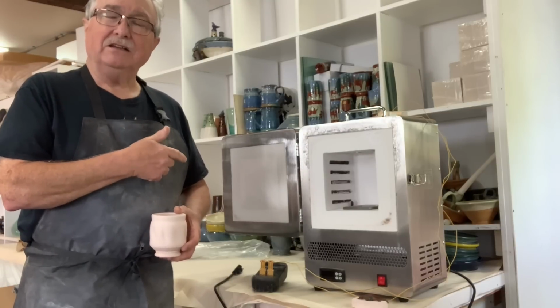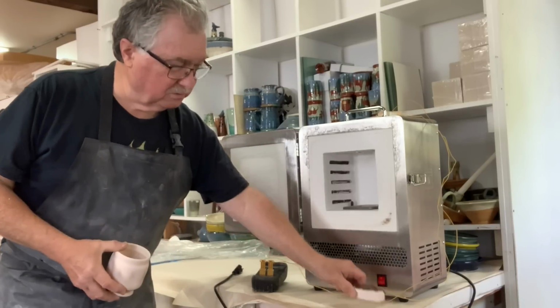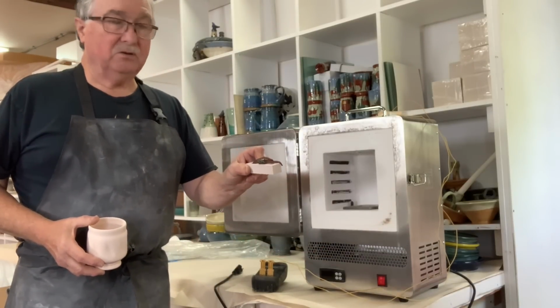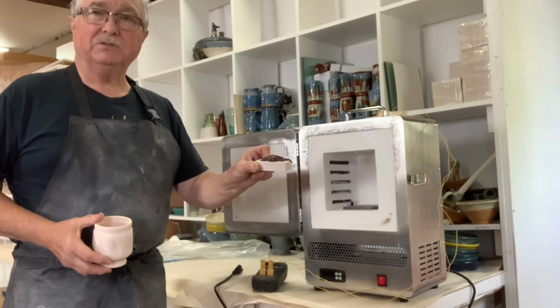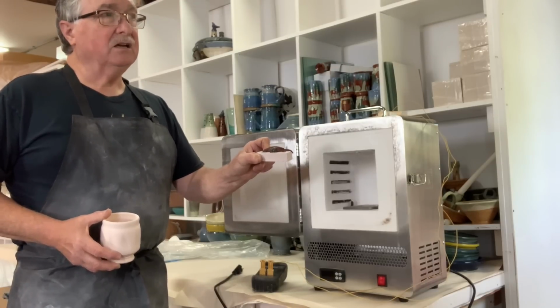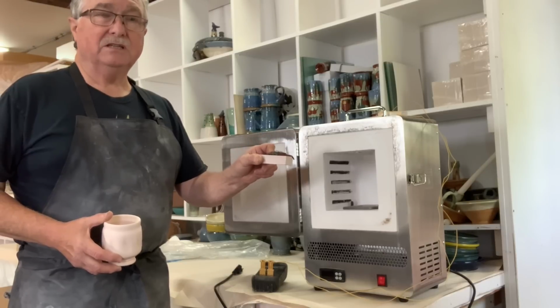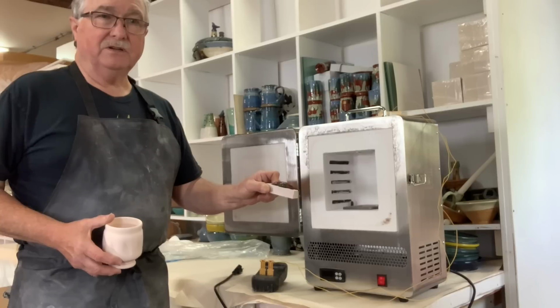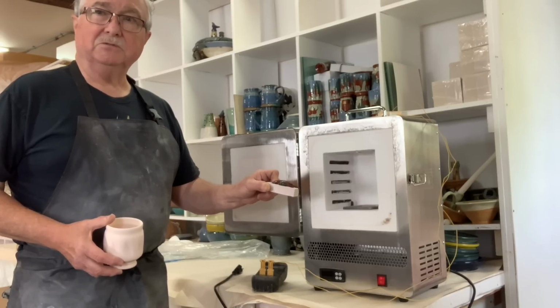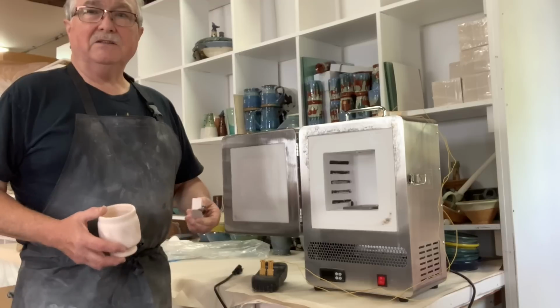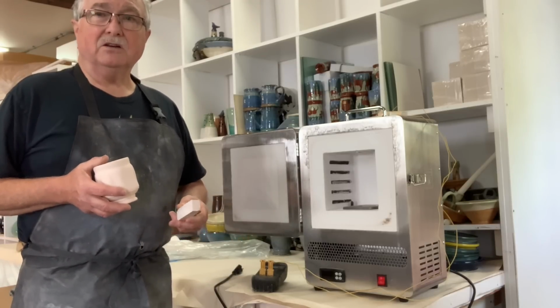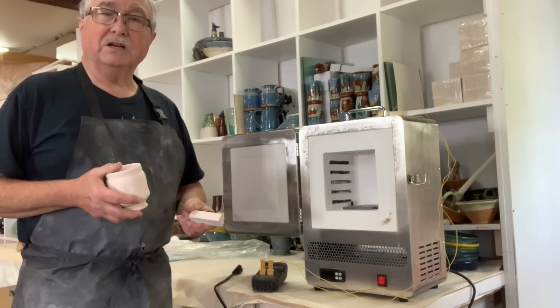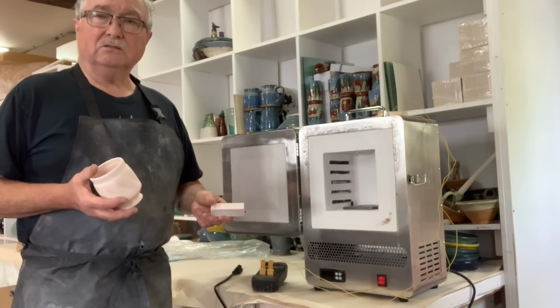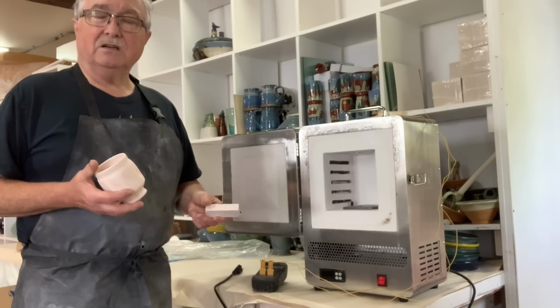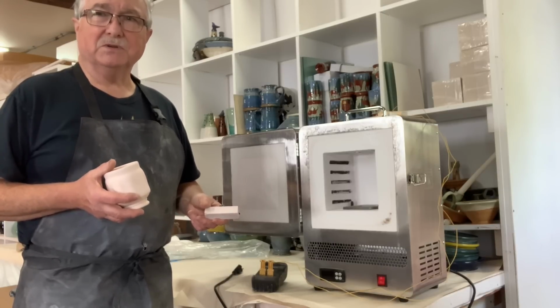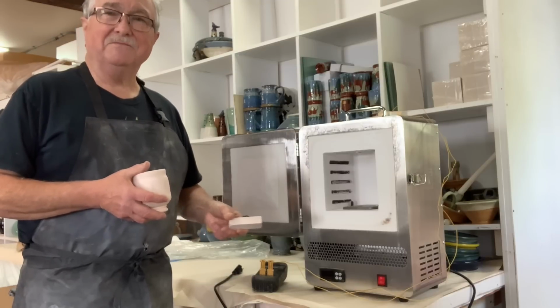Pyrometers can vary, so you should still test your kiln by putting cones in it. This is a cone 06 and a cone 05, fired to what I thought was an 05 temperature, sorry, an 06 temperature, and both of them melted right over, so it's still firing hot, even programmed at 935 centigrade, which is 100 degrees lower than it really should be for those cones to bend. So it involves some testing when you get it, and hopefully my tests are shortcutting that testing you have to do. But I would say that it's a good kiln that needs a few test firings first before you put one of your prize pieces in here.